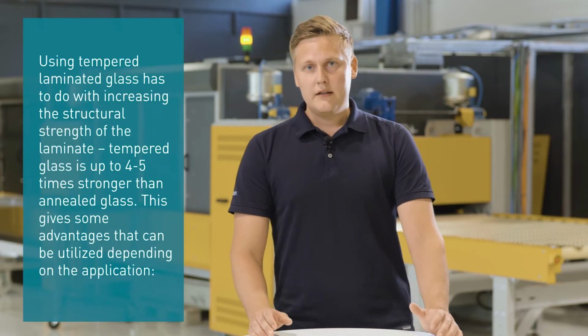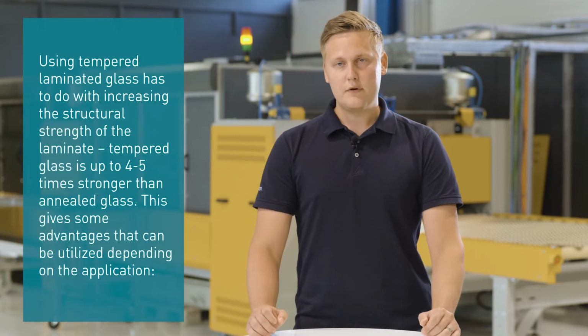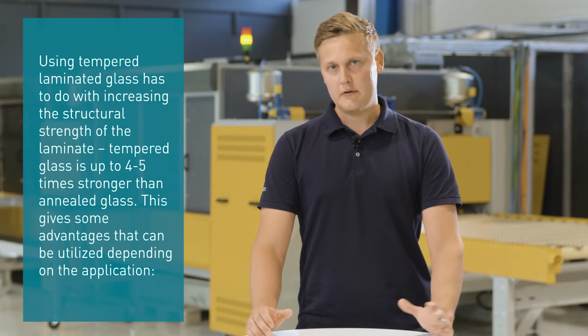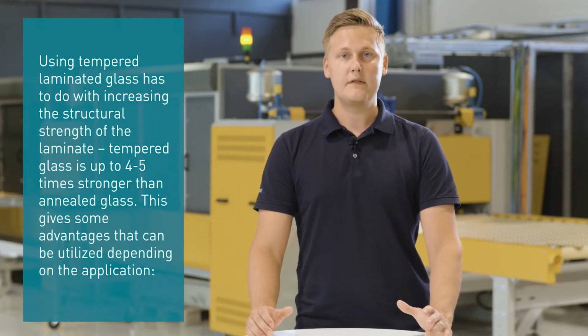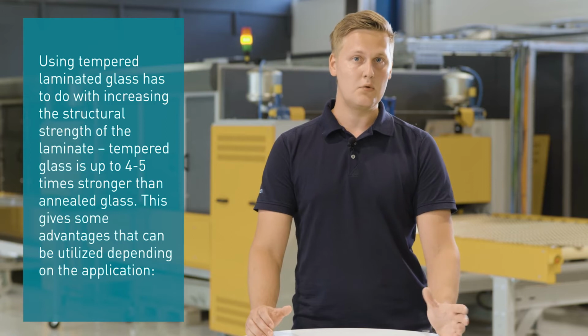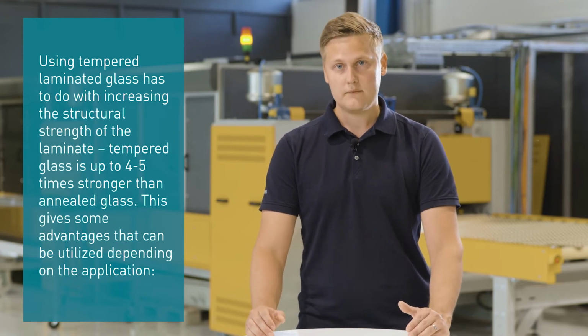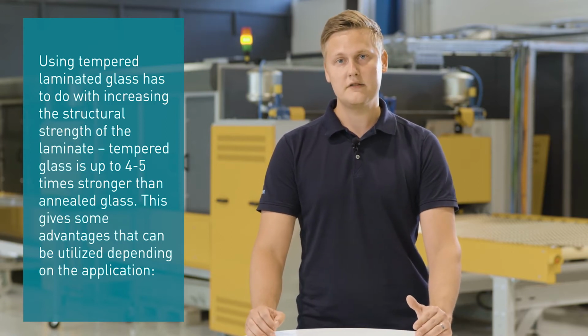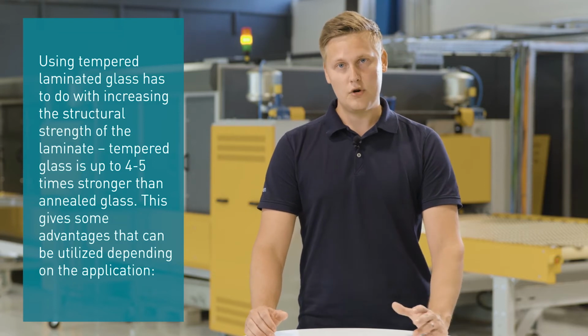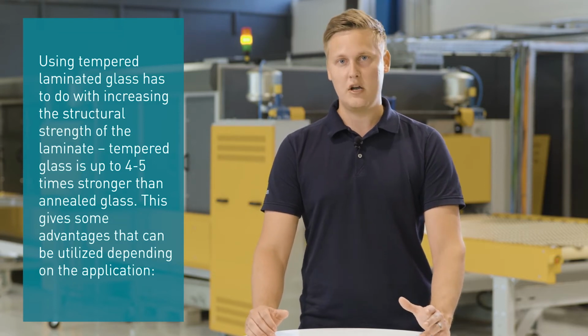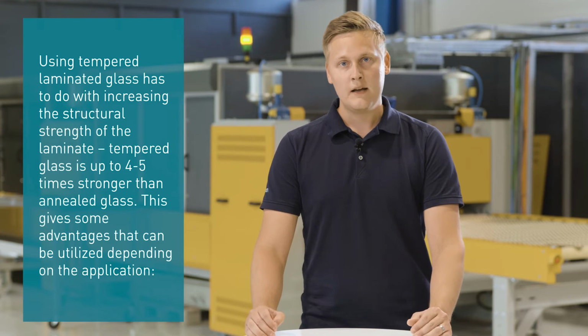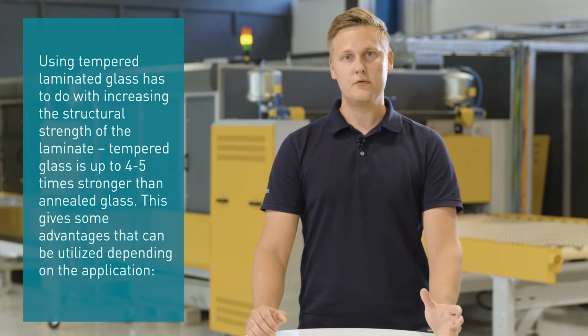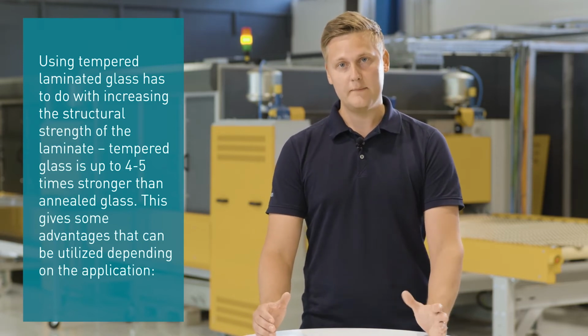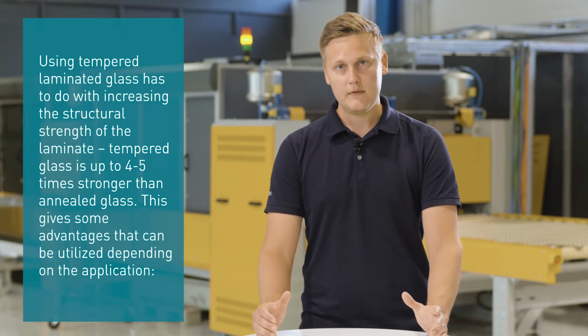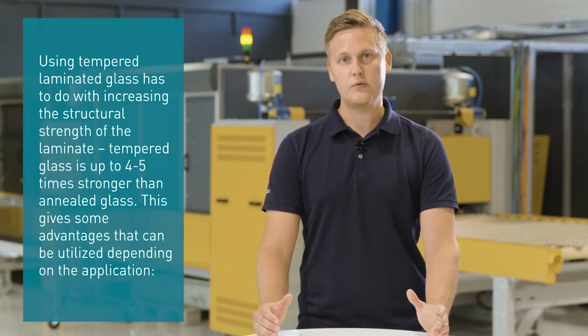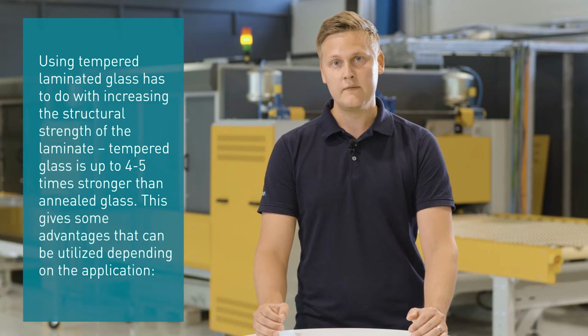But I would say that the advantages of tempered laminated glass are very directly related to other benefits that tempered glass brings to the table when comparing to annealed glass. And the main advantage of these is that it's much stronger than an annealed glass, so normally about 4 to 5 times stronger. And this enables you to bring a huge amount of strength into the laminate itself. And there are many applications where you can take advantage of this.